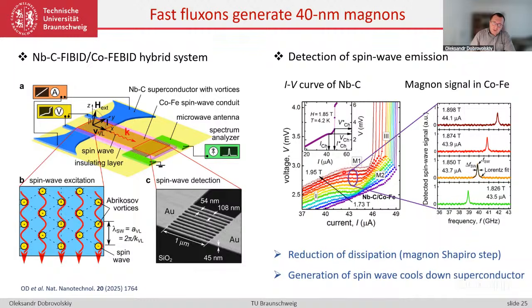And also, these steps are occurring in the flux flow regime, but usually, if you extrapolate the quasi-linear regime, it means that there is missing increase in voltage. And the reason for this missing increase of voltage means that energy from the superconductor is spent towards the generation of spin waves. So generation of spin waves cools down the superconductor, and this can be seen also directly from the vortex velocities, so maximal vortex velocities, which determine the nucleation of the flux flow instability state. So basically, generation of spin waves stabilizes the vortex lattice, suppresses instability, and this effect was actually predicted as a Polaron type mechanism for the moving vortex lattices.